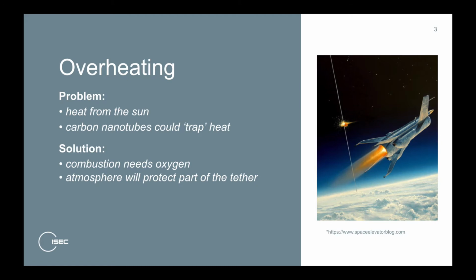While there are studies that show things such as carbon nanotubes igniting when photographed with flash, there is not enough evidence to say that this would be a significant risk to the space elevator, nor that similar results will be seen by heating the tether, as there are other studies which show that carbon nanotubes are very good at being used as a cooling system. Moreover, we know that we need oxygen for material to burn, and so the risk of space elevator fires, at least above the Earth's atmosphere, is negligible.